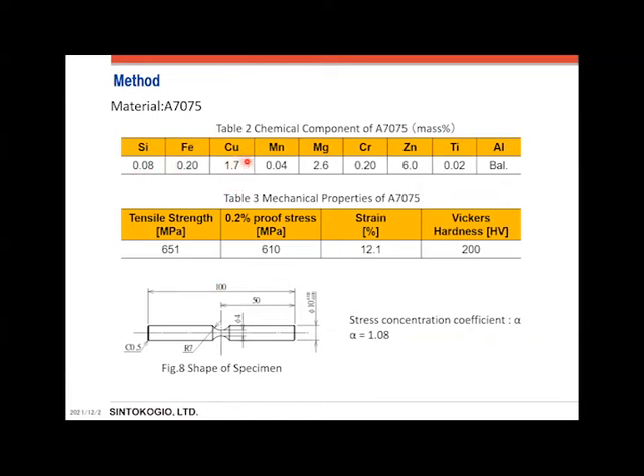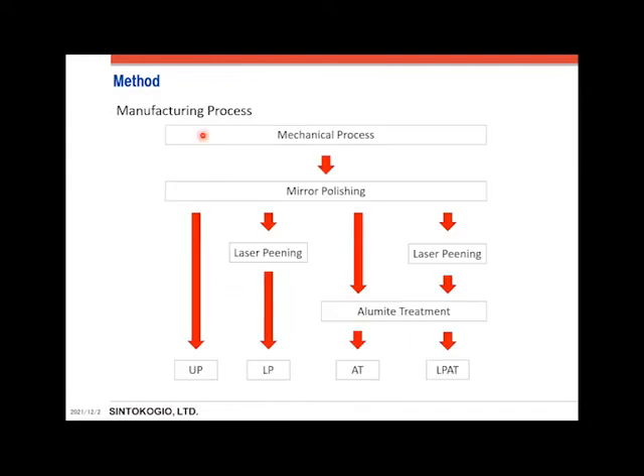So A7075 was used as the specimen material. Table 2 and Table 3 show the chemical components and the mechanical properties. Figure 8 shows the shape of the specimen. The stress concentration coefficient of the test specimen was made to be 1.08. This page shows the manufacturing process of the specimen. The specimen that has been mechanically processed and mirror polished is called UP. After that, the laser peened specimens are called LP. On the other hand, the alumite treatment specimens are called AT. Both laser peened and alumite treated specimens are called LPAT.